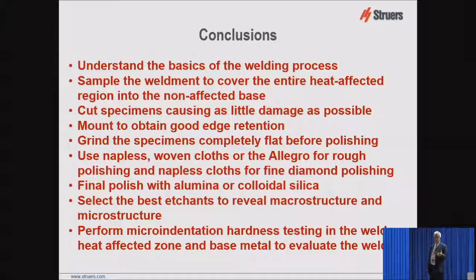The problem here is when you cut something, you don't know what the depth of damage is that you made. And when you're grinding, you don't know how much you're removing unless you sit there with a micrometer measuring the change in thickness as you're grinding. I've seen in the literature, I don't know if any of you do nano hardness testing, very low loads, but in nano hardness testing, you'll see more junk data than any other subject I've ever seen, because people aren't measuring the hardness of the metal, they're measuring the residual damage left that they didn't remove before doing the hardness test.